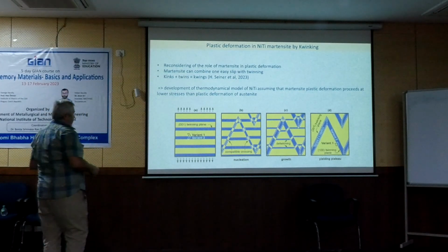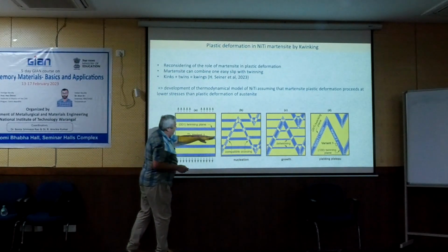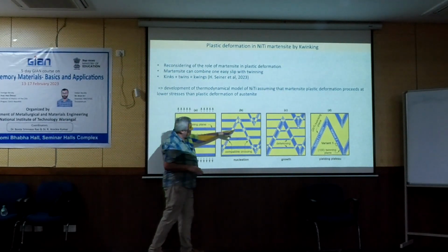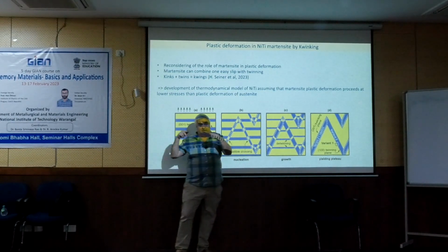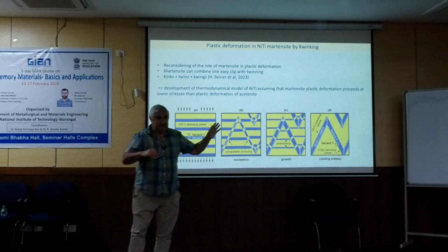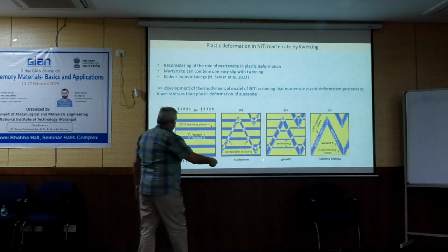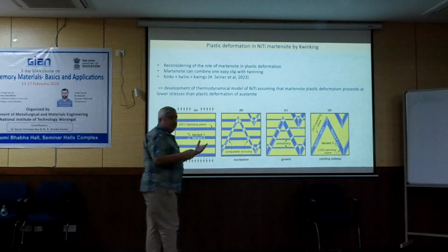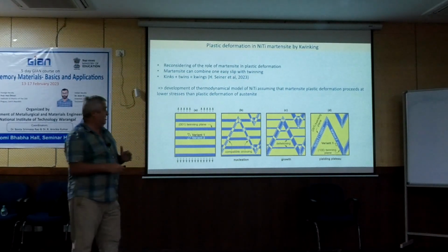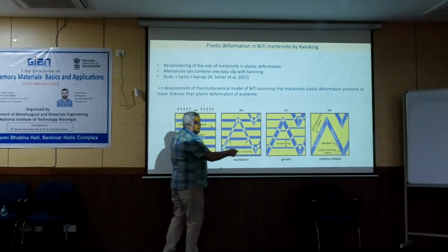But what the material will do, even though the shear stress into this shear is zero, it will start to generate such a pattern which you can observe if you look by the microscope on the side of this stack of papers. And this is exactly what happens in geomaterials. So you see such bands, and these are basically the bands which we see in the TEM, where along these interfaces the strain is compatible.